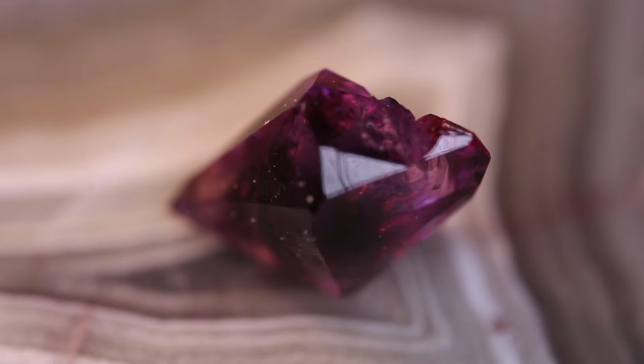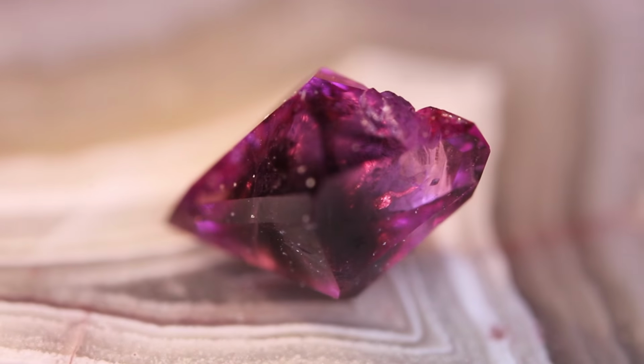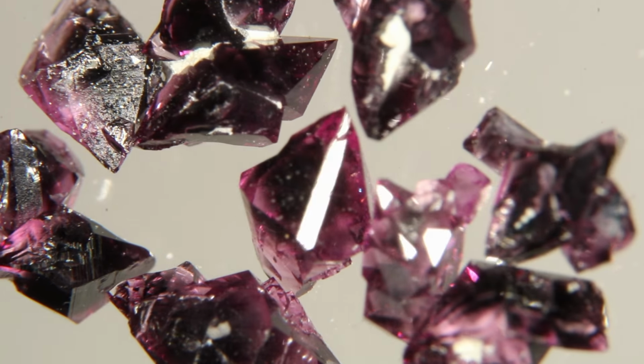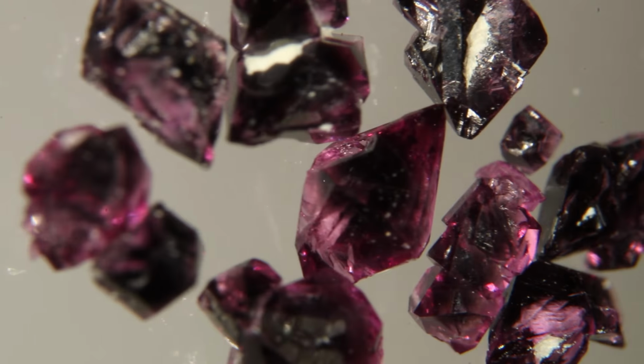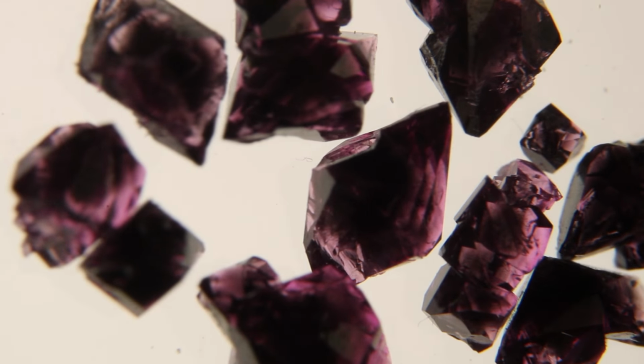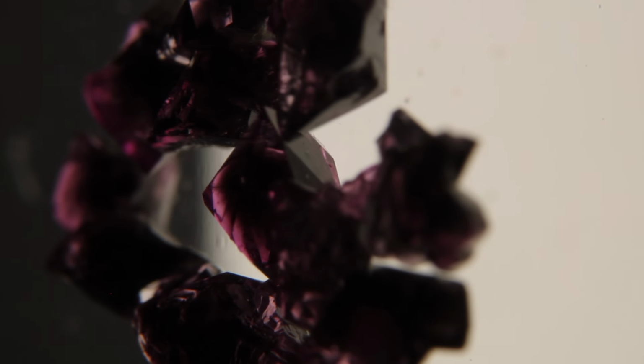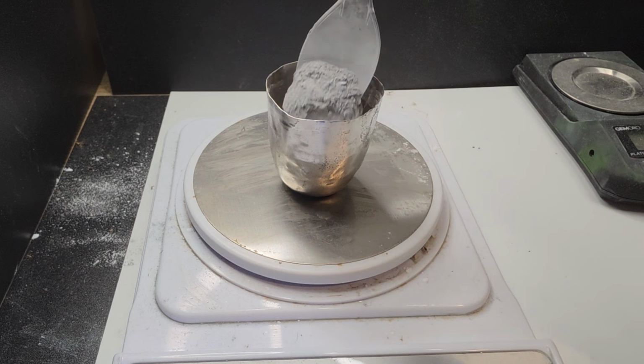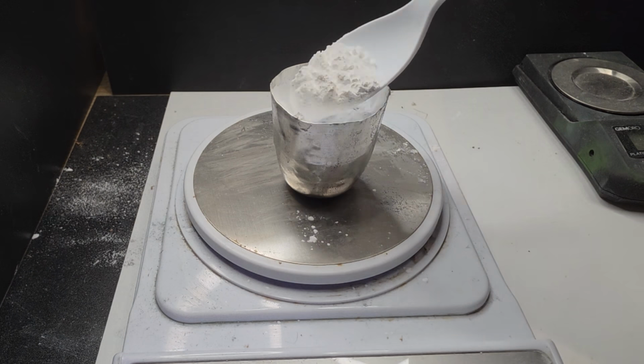These crystals weren't just bigger, they also had a totally different crystal form. These hexagonal bipyramids that look a lot like how sapphires form in nature, and which are often called a dogtooth. They also had a dark core, which could have either been from contamination or from growing too fast and absorbing too much chromium. So I ordered some higher quality tungsten oxide, and while I was waiting, I tried to do